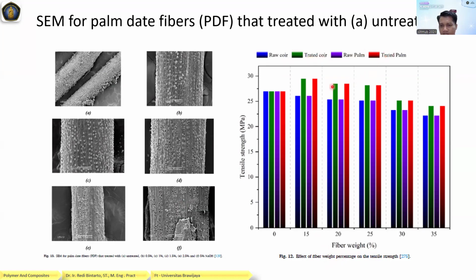For treated palm, the highest is 15%. And for raw palm, untreated, it's the same. We can see the lowest is 35. Treated palm fiber, raw palm. So this is the difference between raw and treated. When they add NaOH, they can increase the bonding between the fiber and the matrix, and so increase the tensile strength. That's the point: which is the best between the treated and untreated.